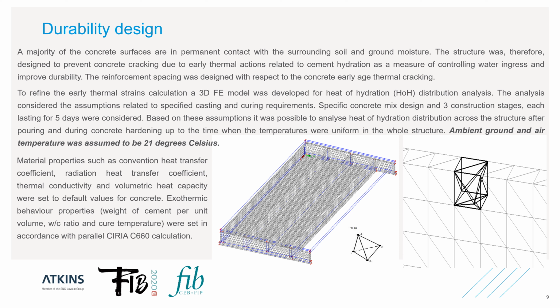A specific concrete mix design and 3 construction stages, each lasting 5 days, were considered. Based on these assumptions, it was possible to analyze the heat of hydration distribution across the structure after pouring and during concrete hardening, up to the time when the temperature was uniform in the whole structure. Ambient ground and air temperature was assumed to be 21 degrees Celsius. Material properties such as convection heat transfer coefficient, radiation heat transfer coefficient, thermal conductivity, and volumetric heat capacity were set to default values for concrete.